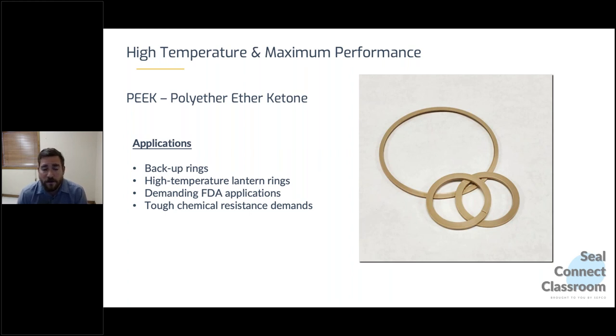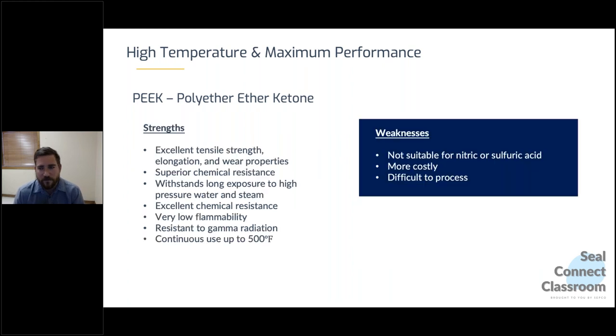PEEK is FDA approved, so in these really rigorous FDA applications, PEEK is an absolutely wonderful choice. It has really good chemical resistance as well, even better so than PTFE. So those tough chemical applications, PEEK is great. Again, excellent tensile strength, excellent elongation, really good wear properties, really good chemical resistance. I mean, it is just a fantastic material. It's not suitable, however, for nitric sulfuric acid. It is more costly, and it can be difficult to process.